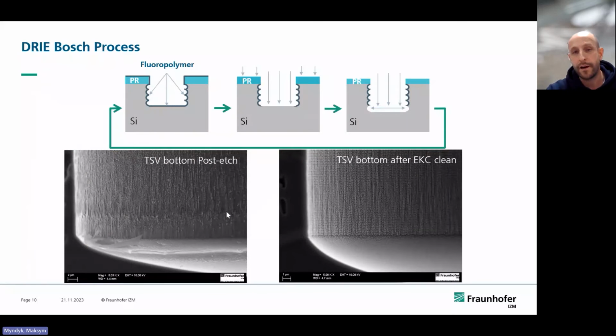Probably all the participants know the Bosch process much better than me, but in the Bosch process we have a cycle of three very important steps. One step is that fluoropolymer is deposited on the walls. After that, the fluoropolymer is anisotropically etched from the top. The third step is an isotropic etching of silicon using SF6 plasma gas. These cycles repeat all the time, and using this process it is possible to etch different dimensions or geometries of TSVs.